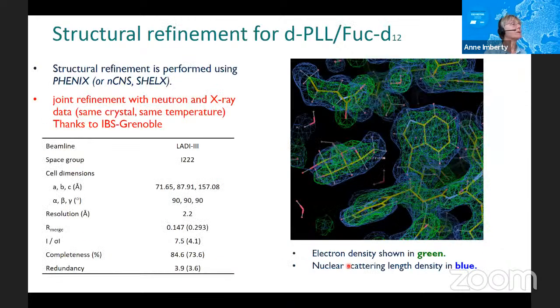So next step is refinement. And as was said by Mark Johnson a moment ago, it's better to have in parallel neutron and X-ray data. So in this case, what we do is that we took the same crystal that was used for neutron diffraction, and at room temperature, in fact, it was at IBS because there was a problem at the moment with the X-ray at ILL, but at IBS, we did exactly on the same crystal, the X-ray measurement. So at the end, you can compare and you can complement the data.